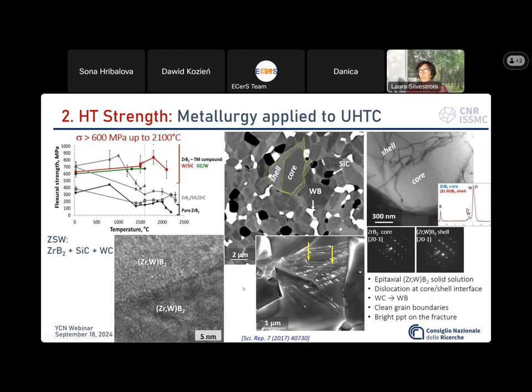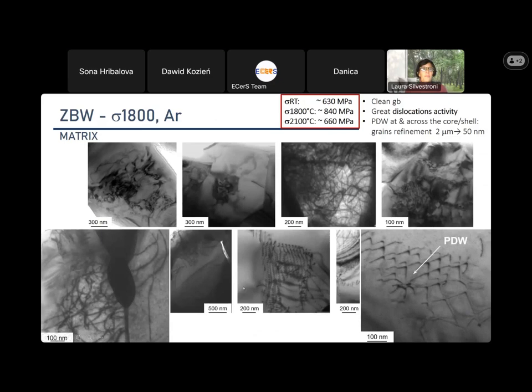To get deeper into it, I did some TEM analysis on the broken bars after high temperature strength testing, and you can see an intense dislocation activity in the boride grains that formed real tangles of dislocations. These intersect and interact with each other, forming polygonized dislocation walls, which actually led to a grain refinement from the original micron size down to the nanoscale.